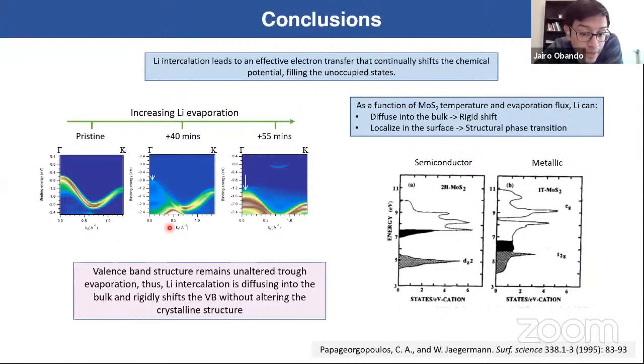This is lithium yielding electrons to the molybdenum disulfide, in which the crystalline structure is not modified. This is why we can observe the same bands shifted, and even when the Fermi level has been shifted enough, we are able to resolve the unoccupied band. So I encourage you to ask me in the question session what is expected to happen in the second situation that we are not seeing in our case.